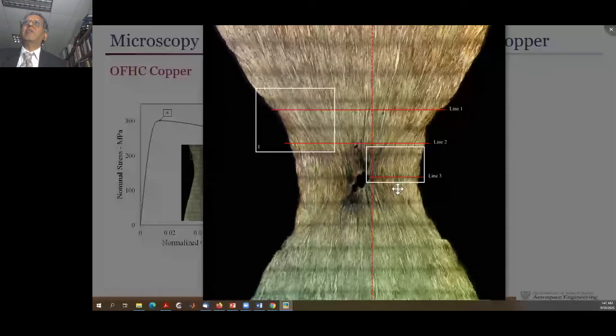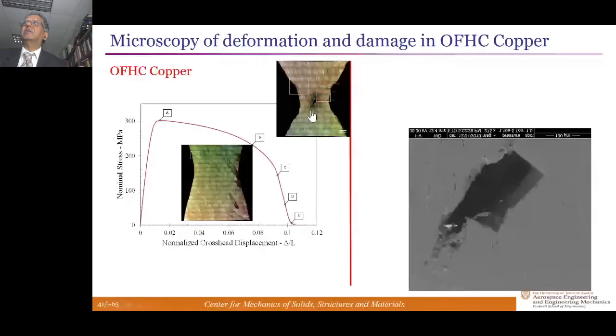If you zoom in even greater to that, you could see at the center of the intersection between the two, there is a cavity. And this cavity is rectangular in shape. It has sharp corners. And to make that visible, take the same specimen and look at it under an electron microscope, you could see the corners that have been formed. So it's breaking in a very, very weird way, is one way to put it. It's creating rectangular corners inside of a material.